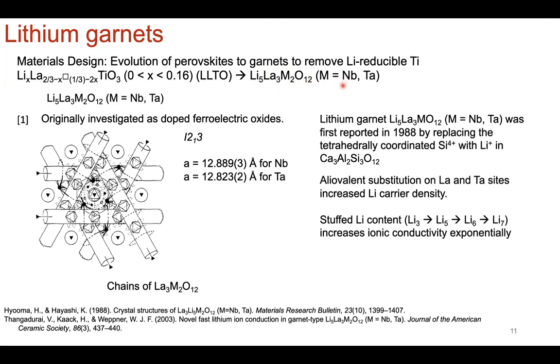Originally, niobium and tantalum were introduced to basically replace the titanium, which is reducible by lithium. Titanium was being reduced, and of course, if your titanium is being reduced, then your original oxide compound is going to fracture, and then it's going to decompose, and it doesn't preserve its original properties.